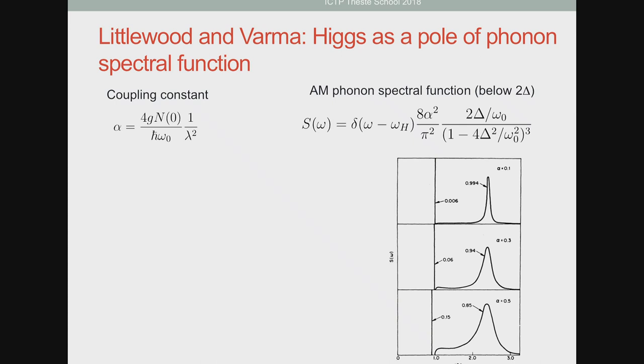So that is good, because that is going to render it more long-lived. And those are calculations for varying coupling constant. You can see here this feature is the amplitude mode of the charge density wave state. And once you cool down below TC, there is a very sharp mode, which in this theory is a delta function. And when you crank up the coupling constant, this goes more and more below 2 delta.